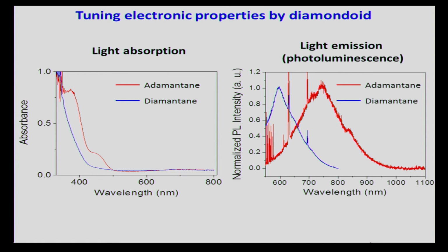And what you have here is that beyond, let's say, 600 nanometer wavelengths, both crystals don't really absorb much light, but you start to see strong absorption with the adamantane around 500 nanometer, that is in the greenish regime. But with diamantane, because of the different arrangement of the copper and sulfur atoms, again enabled by the different interaction between the diamondoid species, now you start to have an absorption edge around 400 nanometers. So this is really a huge 100 nanometer change in the absorption edge, which indicates a large change in their electronic properties. And this is, again, solely enabled by changing the arrangement of copper and sulfur atoms, again enabled by tuning the interaction between the diamondoid species in a non-bonding environment.